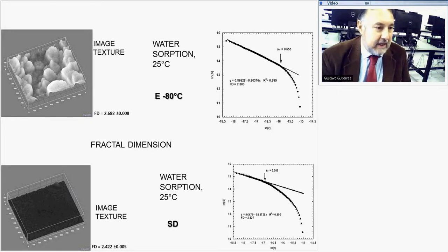We have the image texture for the sample at -80. Here we see the fractal dimension there and the fractal dimension for the spray dry material. But the fractal dimension of that -80 degrees is higher than the fractal dimension of the spray dry material, indicating a more irregular surface for this compared to that material, which can also be seen in the images that we took with the electron microscope.